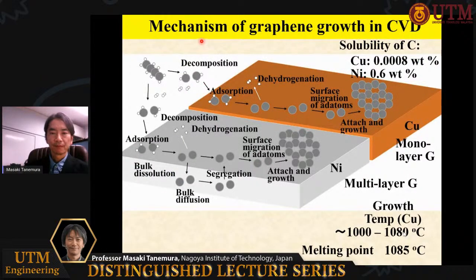This is a mechanism of the graphene growth in CVD. Decomposed hydrocarbon molecules adsorb on the catalyst surface, for example, on copper and nickel. On the copper surface, dehydrogenation of adsorbed hydrocarbon molecules occurs. Then, carbon atoms migrate and agglomerate into graphene structure.